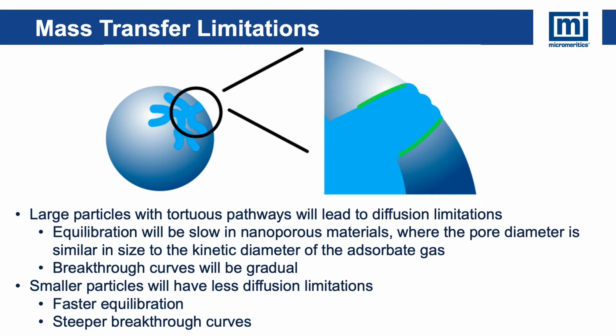Next up, let's talk about mass transfer limitations. Large particles with tortuous pathways will often lead to mass transfer limitations. In general, for microporous materials or any materials where your adsorbate gas is similar in size to the pore window of your adsorbent, equilibration will be slow. What you will see is that your breakthrough curves will be gradual.